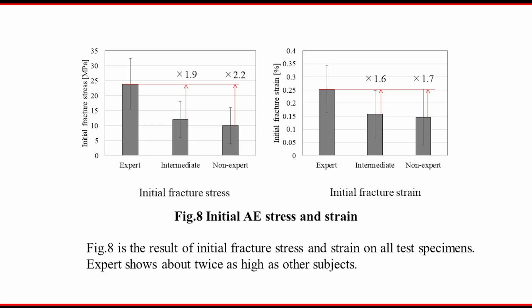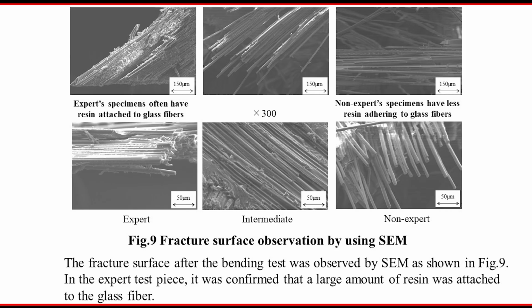So normally we try to understand the fracture behavior. This is a fracture surface taken by scanning electron microscopy. The left side is the expert, the center is intermediate, and the right side is non-expert. You can find thermoplastic resin on the fiber in the case of the expert, and in the case of the non-expert, you cannot see any resin on the fiber, and you can see the glass fiber surface directly.